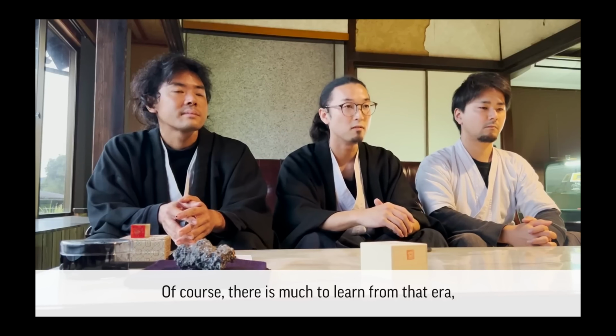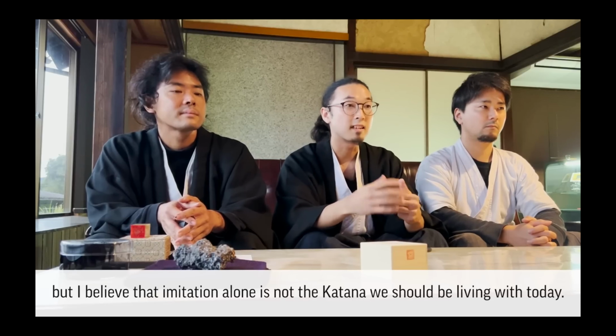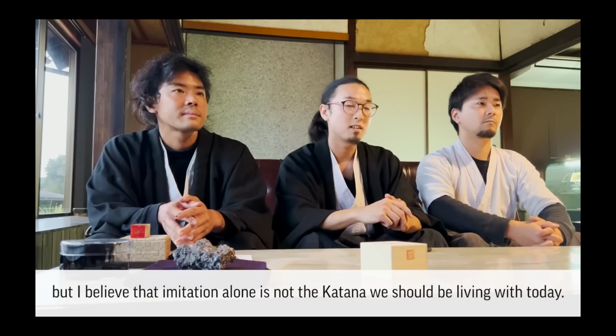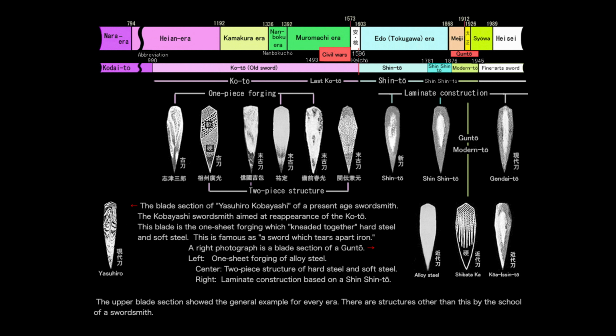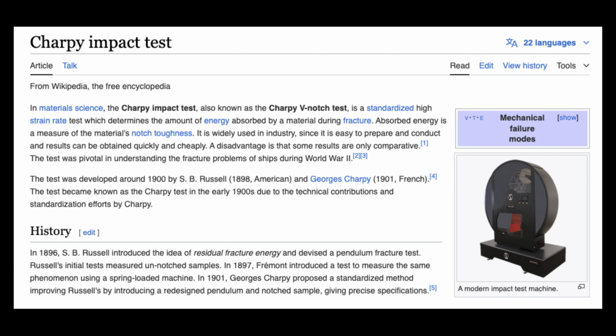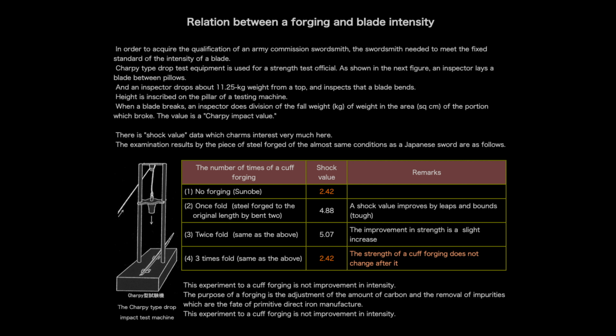If we check apparently the studies during pre-World War II of Gunsuito, Mantetsuto, and Kwantung Army test on gunto around 1937, with the Charpy test, the Gunsuito seem to prove that compared with tamahagane laminated katana, monosteel gunto from modern industry around 1937 had better results of strongness if we drop an 11 kilos weight on a blade from 95 centimeters of height, so the Charpy test.